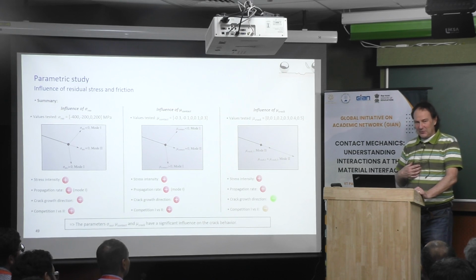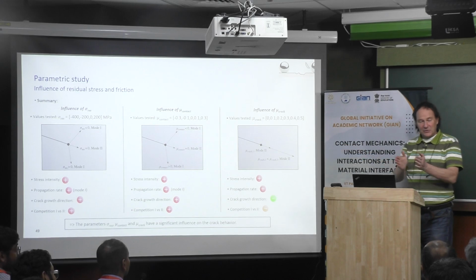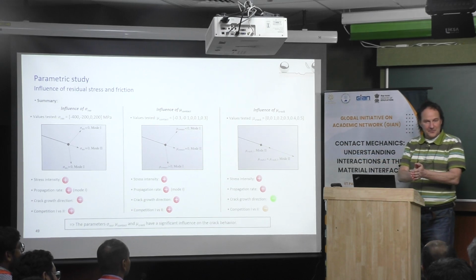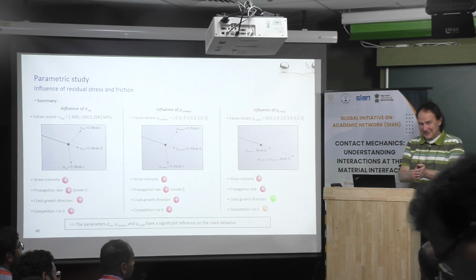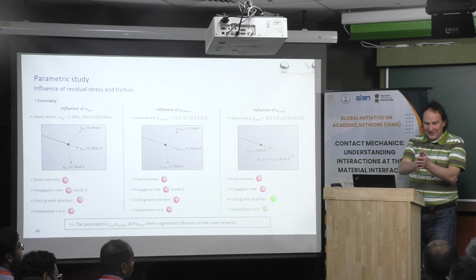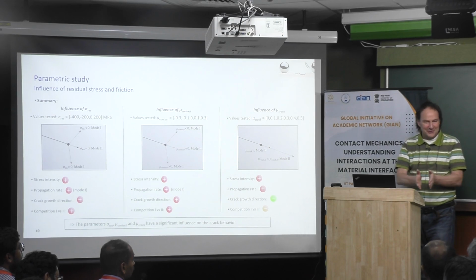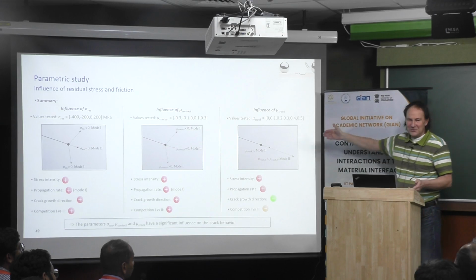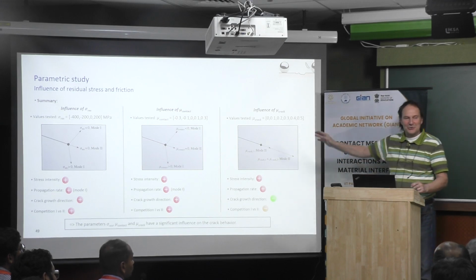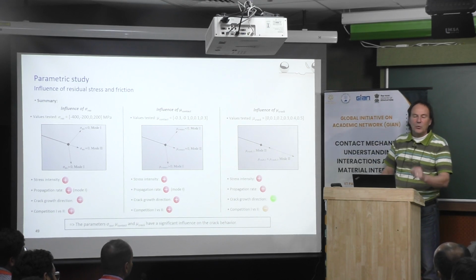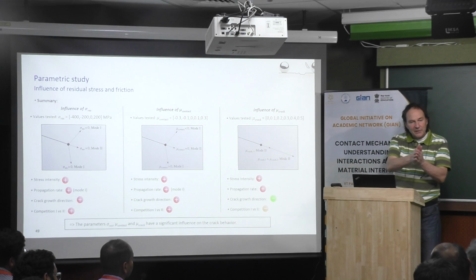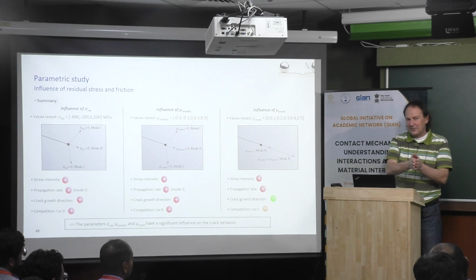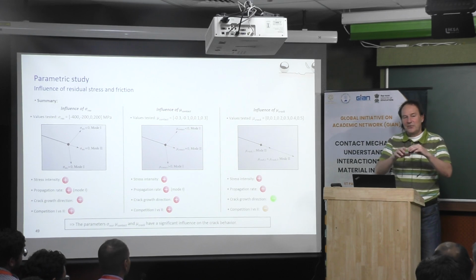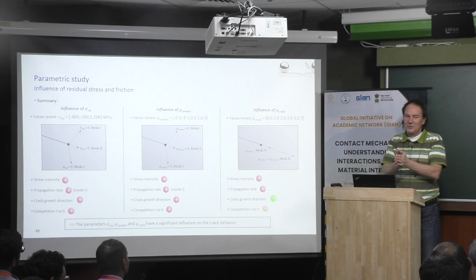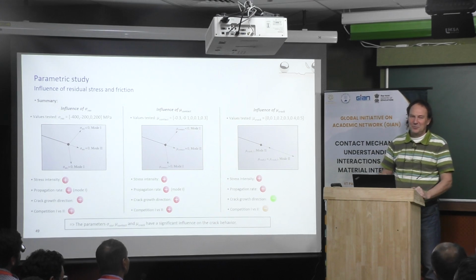I consider that when you have a crack, for me the friction coefficient should be 1 or more. Why? Because the surfaces are not flat. They are like mountains and valleys. It blocks everything. For me, the friction coefficient should be infinite. There is no sliding. But in the literature, they put some friction coefficient. Then for me, it should be 1 or more, and not something like 0.1, 0.2, 0.3. When you have a fresh crack, after a while, of course, because it will be rubbing, it will be wearing, then after a while, you should have something flat, especially when you are far from the crack tip. But nearby the crack tip, it should be close to 1. This is my personal opinion.